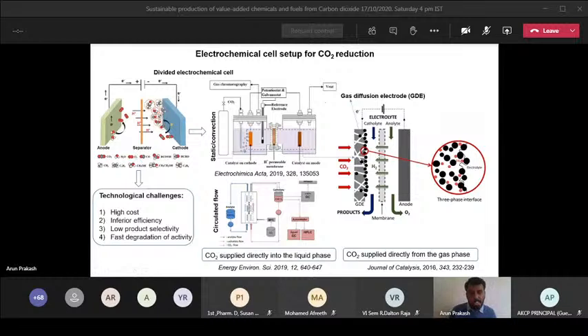So what are the technological challenges? High cost, because you are supplying some potential and using a potentiostat, an electrochemical setup. So this accounts for the cost. Also, you need a good catalyst, so the catalyst preparation cost also matters. And inferior efficiency and low product selectivity. Selectivity is a huge problem in CO2 reduction because multiple products, C1 to C4 products, will be formed. Then fast degradation of activity, because your catalyst cannot hold for a long time. As I told you, it has to withstand at least 500 or 1000 hours, but in reality, within 3, 5 or 10 hours, the catalyst will degrade from the surface. So the fast degradation is an important drawback.